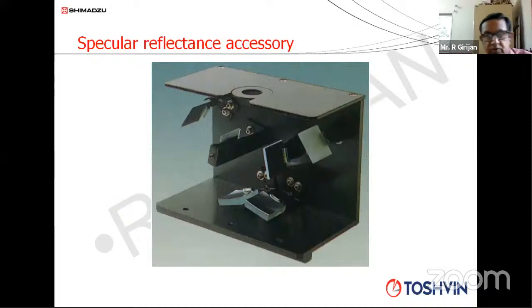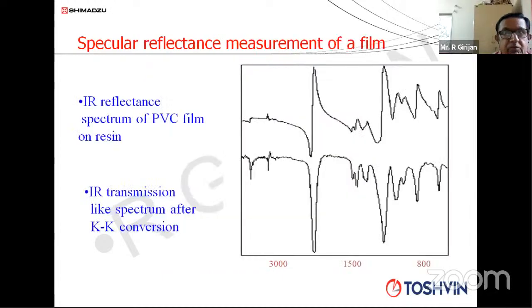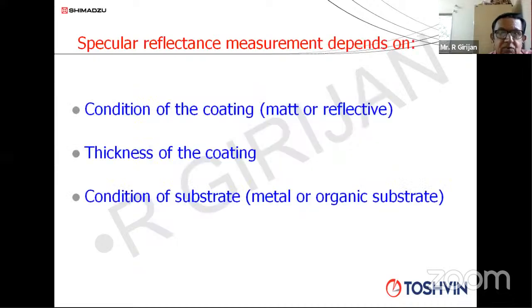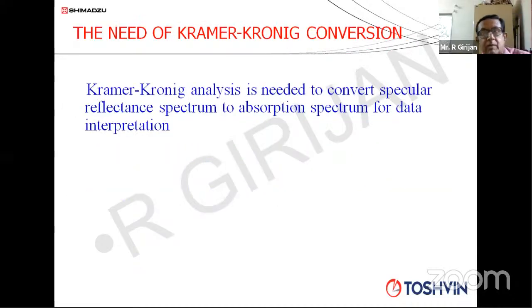And this is how it looks. It is exactly like a DRS attachment, and this also will sit inside the sample compartment. And once you record the specular reflection on a material, you have to again apply a correction factor, which is known as Kramers-Kronig conversion, another mathematical conversion. And Kramers-Kronig conversion is actually converting a specular reflectance spectrum into a normal transmission spectrum.